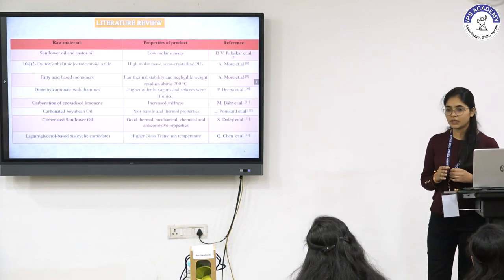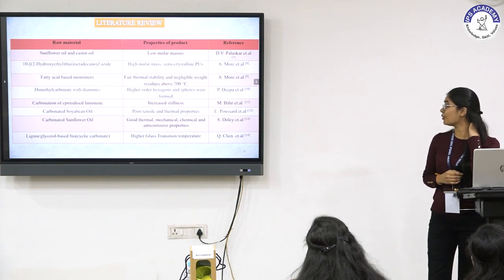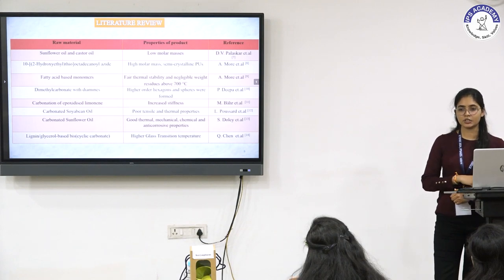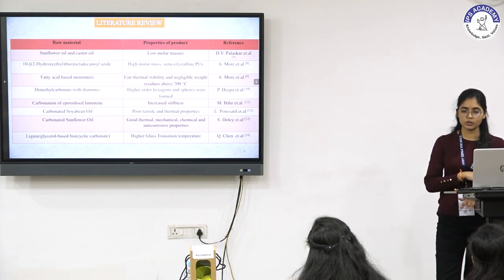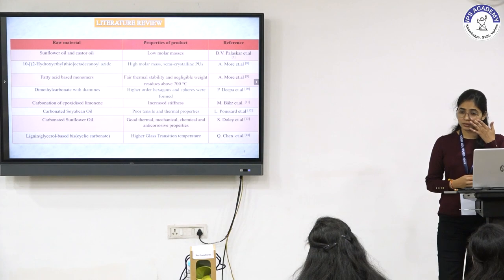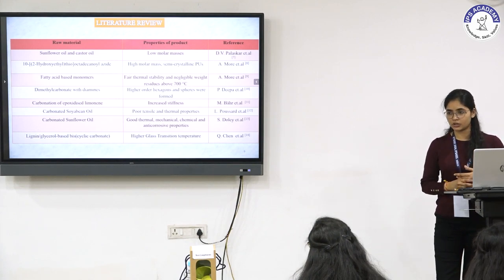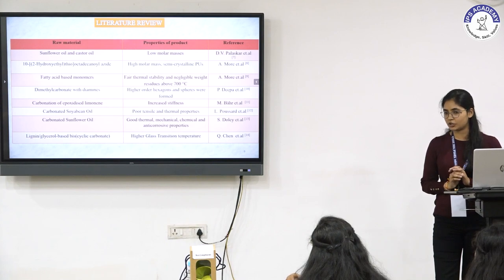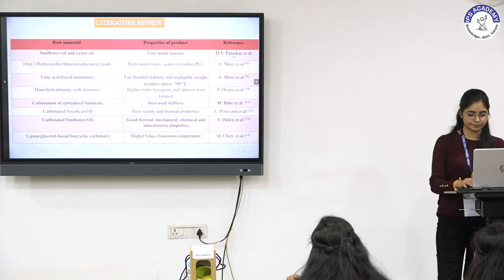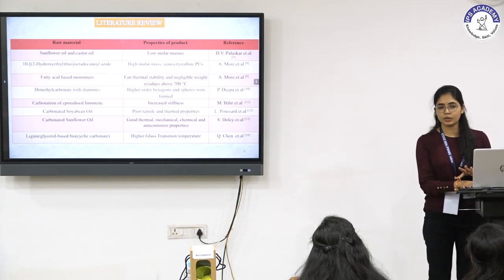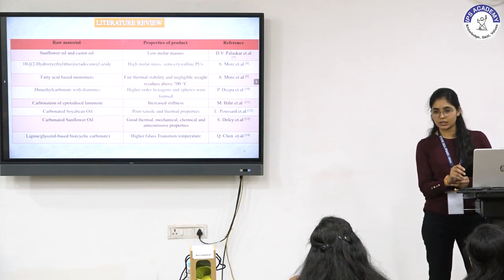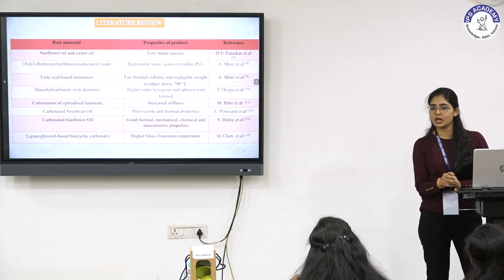Most of the work done in the synthesis of non-isocyanate polyurethanes is in the form of adhesives and coatings. Various vegetable oils such as sunflower oil and castor oil have been used. They are first converted into epoxides, further oxidized, and polyols are derived. These polyols are then treated with carbon dioxide at high temperature and pressure, which further leads to urethane linkage formation when treated with diamines. After this literature review, research gaps were identified — notably that these NIPUs require very high temperature and pressure.